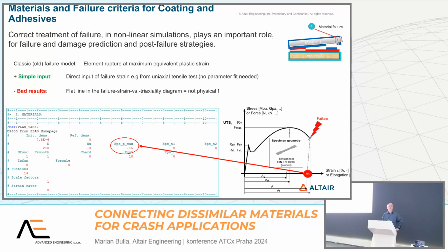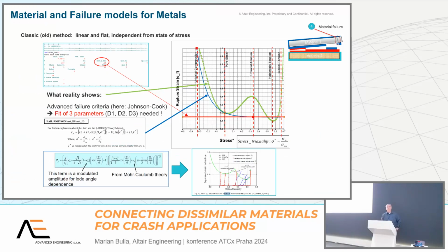But there is of course also a drawback. A flat line in the failure curve versus a triaxiality diagram, which means it's not physical. What does this mean? Here, the maximum plastic failure strain is this one. A flat line, if you compare over triaxiality, which means the ratio between hydrostatic stress and von Mises stress, which helps you to distinguish the load case. Compression, shear, tension, because the materials behave differently if you load them, for example, in compression. Usually, the materials can go to a higher strain until they fail, whereas in tension, they are critical. Shear can be somewhere in between, and so on.